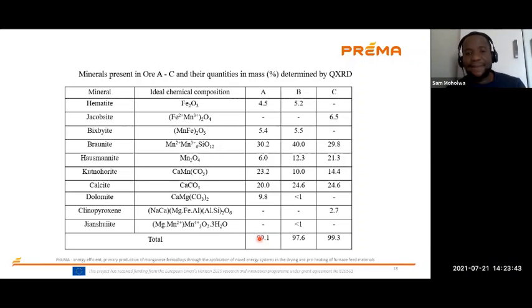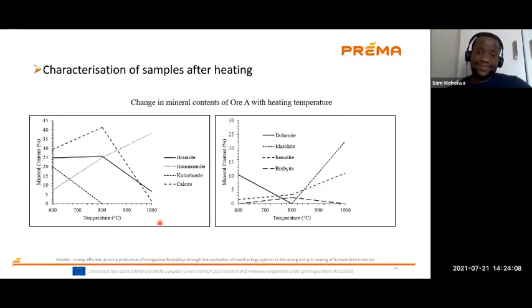This is the mineralogy of the ores that we utilize in this study. From this result, you can see that the main source of manganese from these ores mainly comes from braunite, haussmannite, and kutnohorite. As mentioned before, we did a characterization of the samples after we taken them through the kiln.